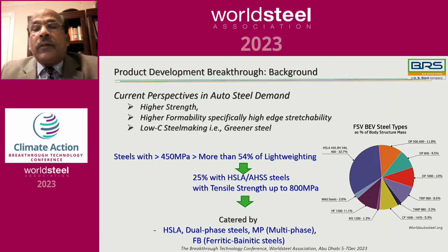And if we consider a typical passenger vehicle, 54% of the lightweighting of a vehicle is through the use of steels with tensile strength of 450 MPa and higher. And out of that 54%, 25% constitutes steel with tensile strength up to 800 MPa. And these steels are catered by the introduction of HSLA, dual phase steels, and multi-phase steels. We also sometimes call them complex phase steels, and ferritic bainitic steel for higher edge stretchability.